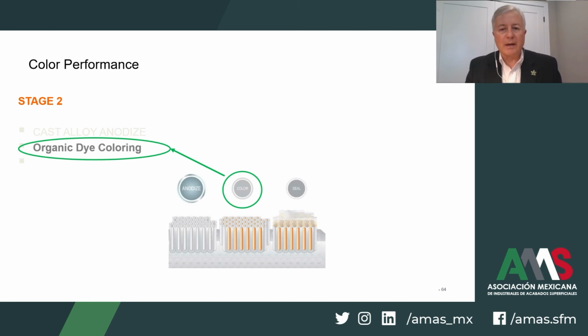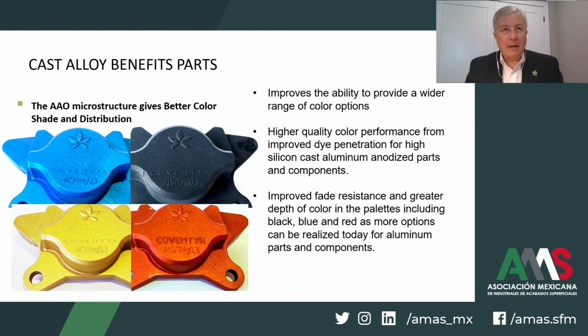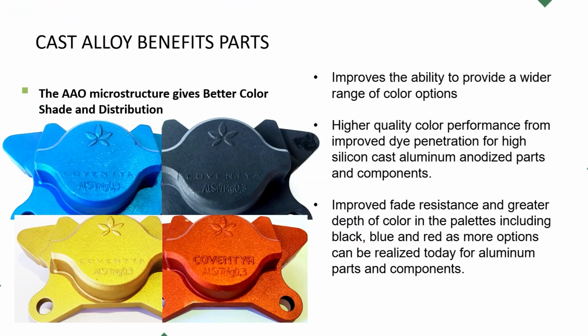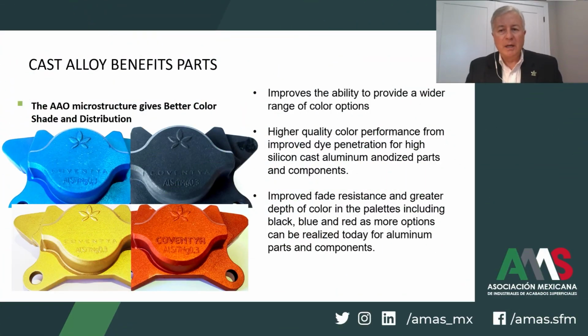The process for cast alloy anodizing provides the ability to improve the color performance, both during the processing of the cast alloy parts, but also when they've been delivered to the end customer or for the final intended end application. As shown here, there are many color benefits to parts incorporating the stage 1 and stage 2 of the process. We can provide a wider range of color options. The higher quality color performance from improved dye penetration into the thicker layers with more pore definition is a very integral, important part. We experience improved resistance to color fading over time, and the depth of color in the palettes, including the black, blue, hue, reds, are important options that are realized for aluminum parts and components.